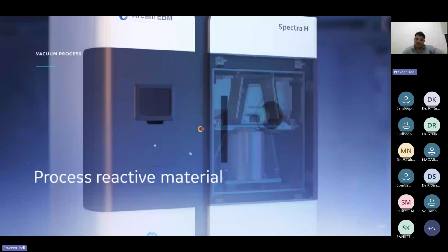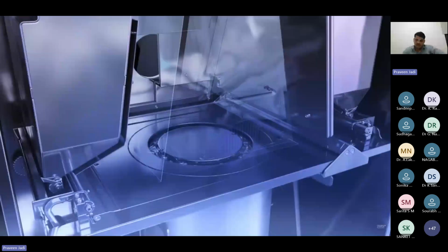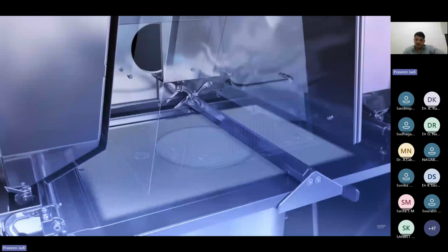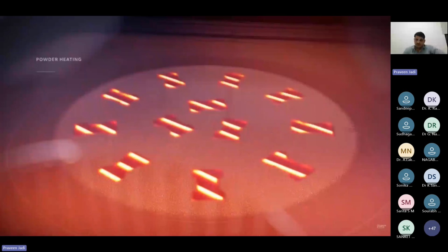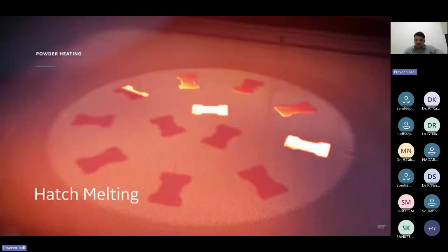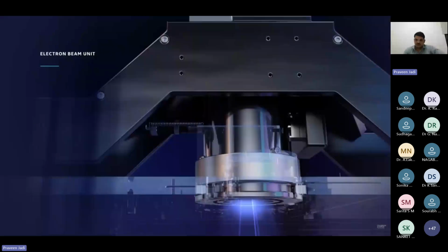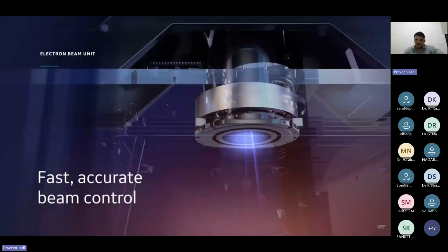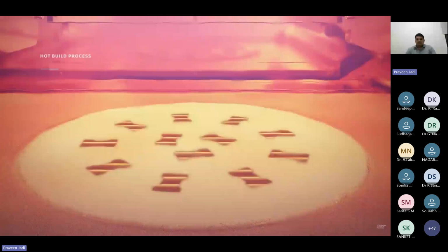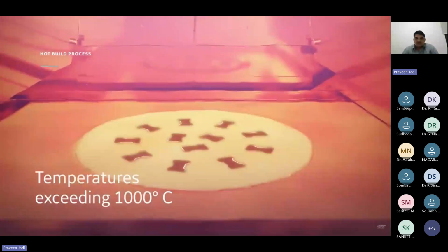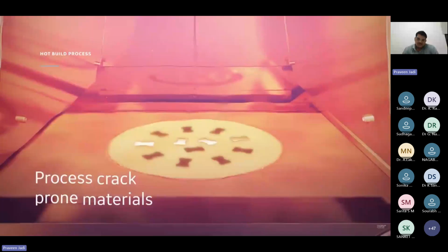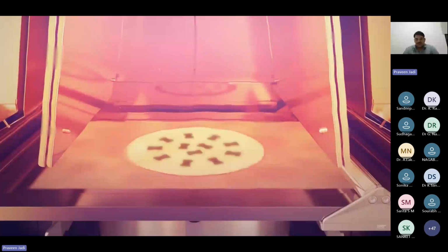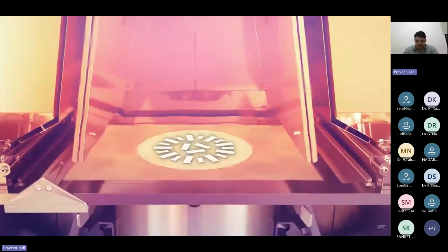Next, Arcam EBM's powder layering system evenly distributes a thin layer of powder on the build area. A powerful 6 kilowatt electron beam heats the powder bed to optimal ambient temperature and then proceeds to melt the powder. First, contour melting and then hatch melting. The electron beam unit generating the beam contains no moving parts, allowing for extremely fast and accurate beam control. The build environment is kept hot, reaching temperatures exceeding 1000 degrees Celsius, resulting in no residual stresses and allowing for the processing of crack-prone materials. As each layer is completed, the build is lowered and a fresh layer of build powder is raked over it. This process repeats, growing the build one layer at a time. When the build is complete, the tank is extracted and the Arcam EBM machine is prepared for the next build.